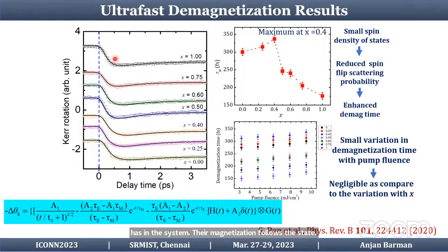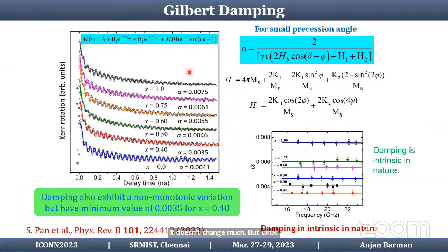And here is the ultrafast demagnetization result. It clearly shows that there is a non-monotonic variation in the demagnetization time. And you can see that demagnetization time increases and becomes maximum at 0.4 and then rapidly decreases. With fluence, it doesn't change much. But what about the damping? This is the Gilbert damping, and you can see this is the damped precessional motion. We modeled it with this equation, and from here we use all these complex expressions to find out the damping, and this is the damping as a function of frequency for different composition. And we can see damping also does not follow a monotonic behavior, but it's non-monotonic.